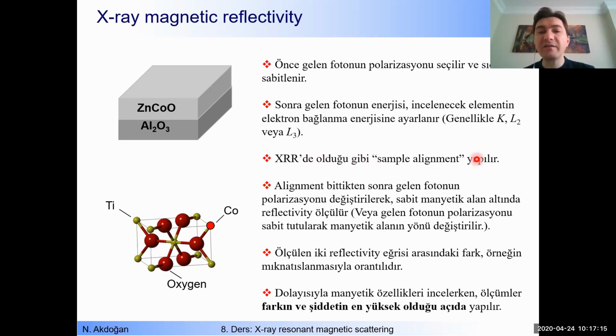Then we do sample alignment as we have done for the X-ray reflectivity experiments. After the alignment, we can carry out two types of measurement. One is that you apply a magnetic field and then measure the reflectivity. Then you change the polarization of the light and measure another reflectivity. Or you can do it like this. You can fix the photon polarization and then apply a magnetic field in that direction, measure reflectivity, reverse the direction of the magnetic field, measure the reflectivity again. This is another possibility to carry out these experiments.